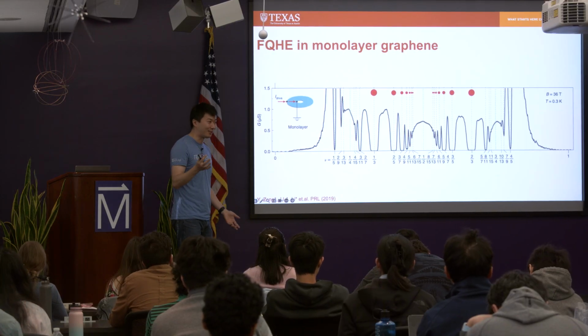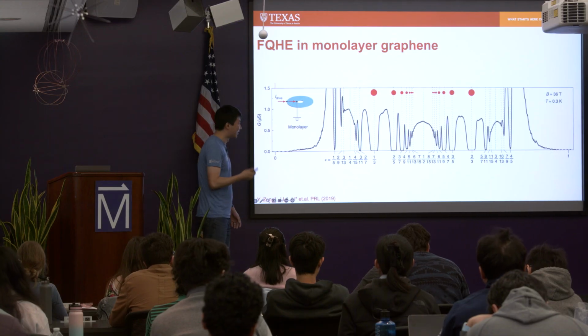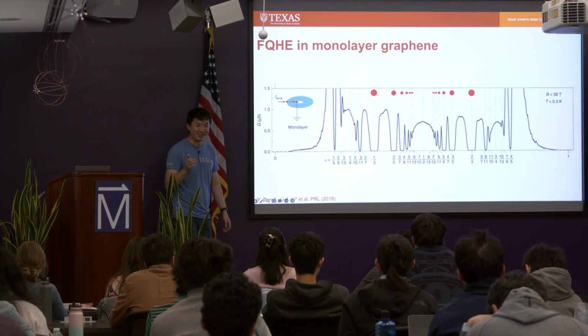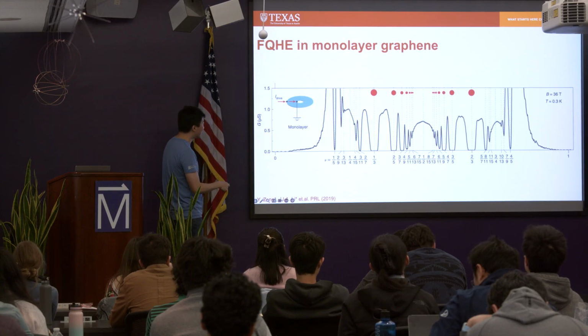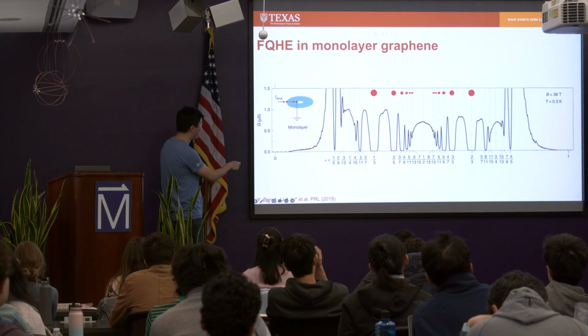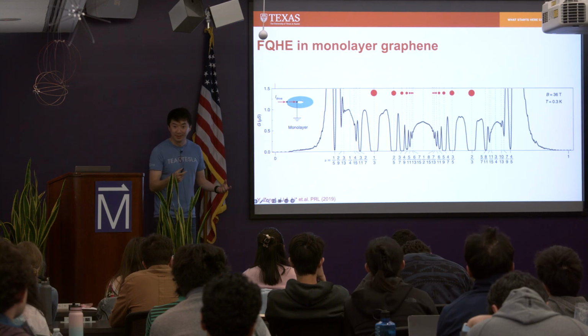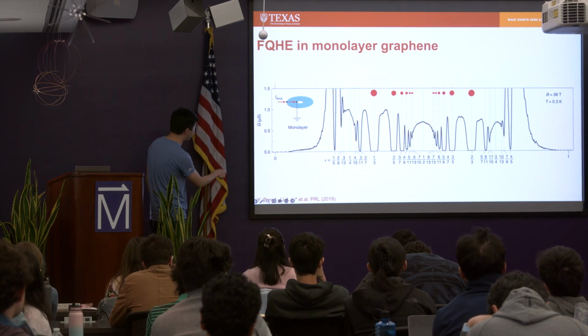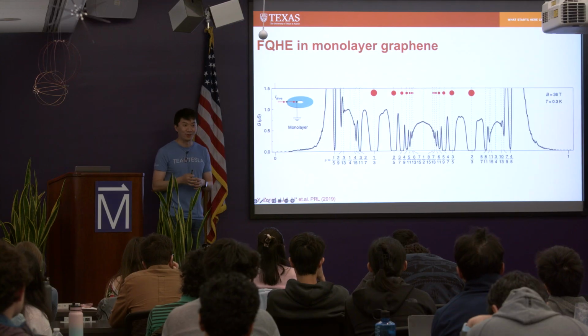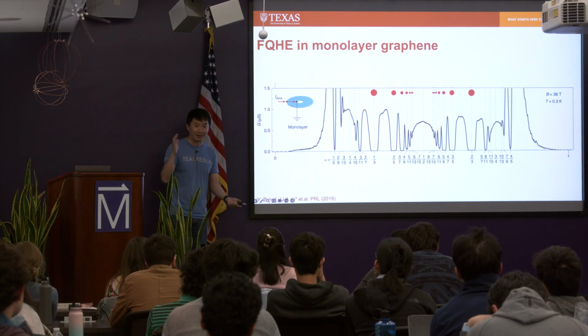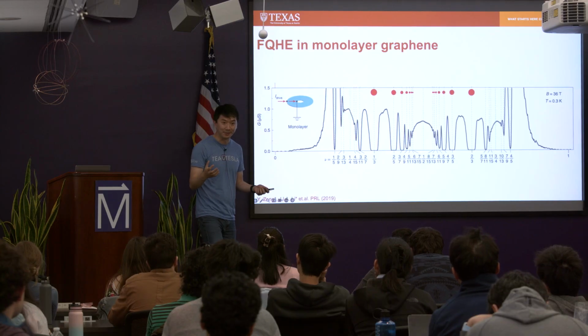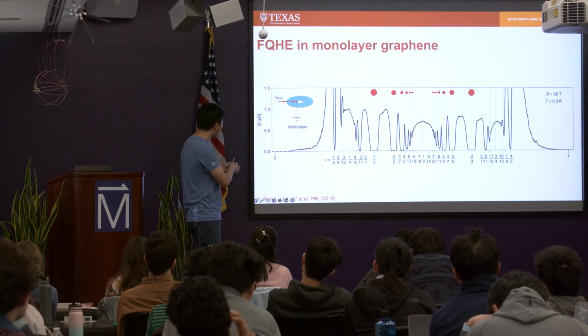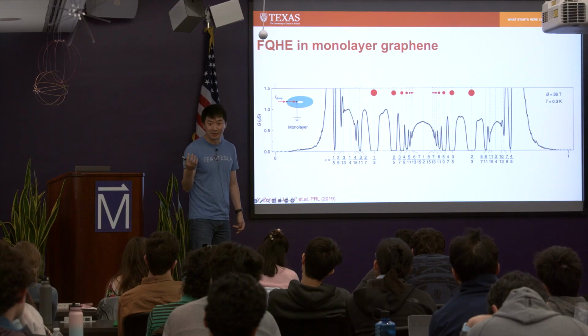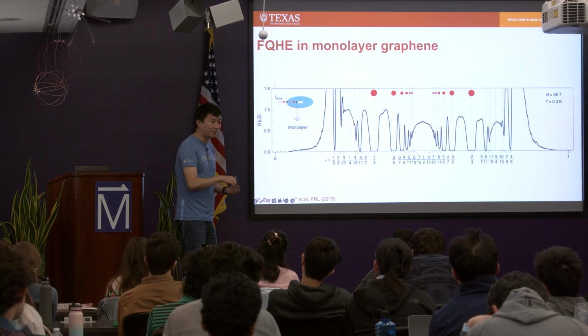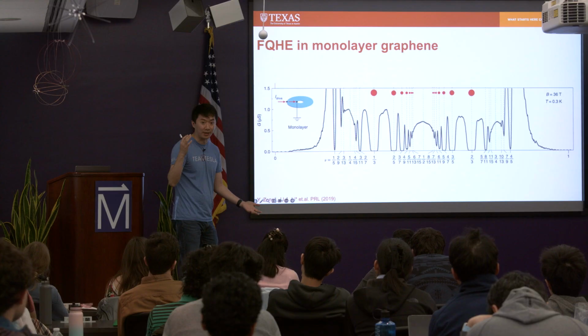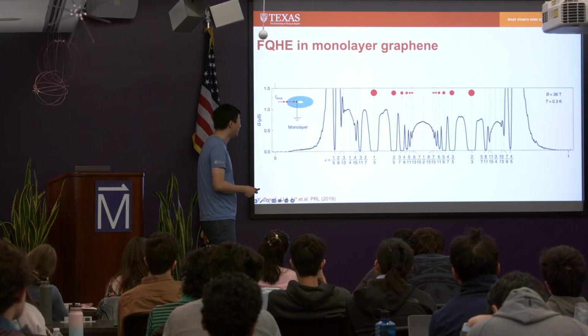You guys have already heard a lot about the composite fermion model. But I think for the purpose of this talk, it's still necessary for me to go into it a little bit. This is a bulk measurement conducting monolayer graphene that's patterned into a single Corbino geometry, right? So the y-axis here is bulk conductance. When you have a fractional quantum Hall effect, there's a charge gap developing, which means that the ground state is incompressible. In the Corbino geometry, it will show up as an insulator because there's no free charge. To excite a quasi-particle, you have to overcome a really large energy gap, right? So at low enough temperature, it's just insulating.